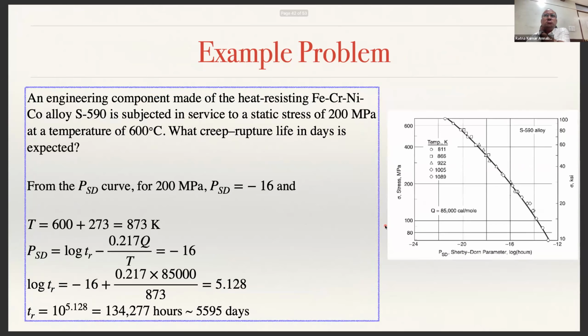Okay, so here you have an engineering component made of certain material subjected in service to a static stress of 200 MPa at a temperature of 600 degrees Celsius. What creep rupture life in days is expected?